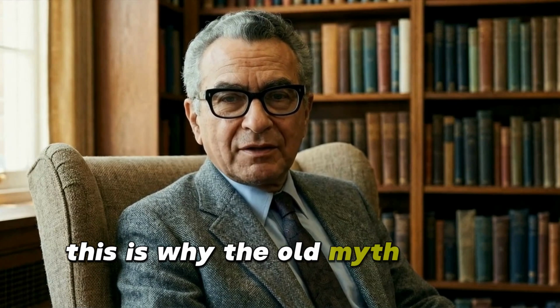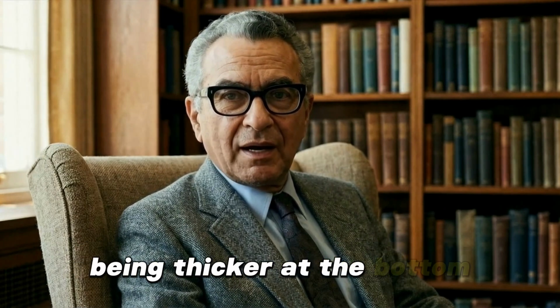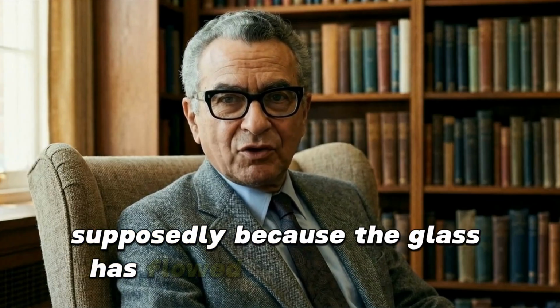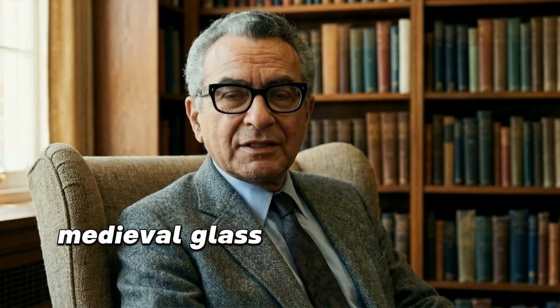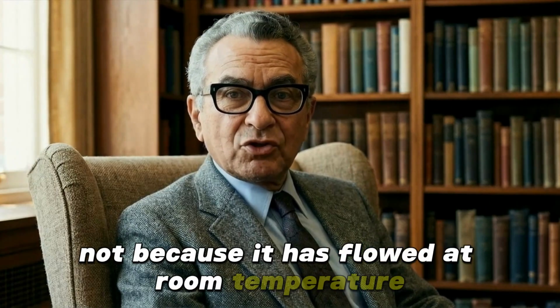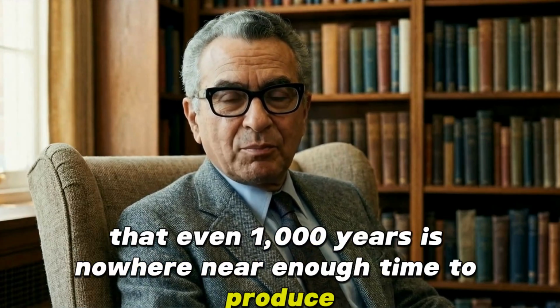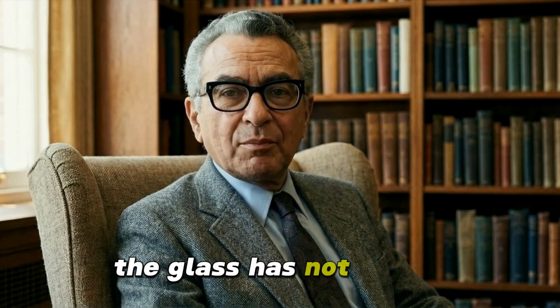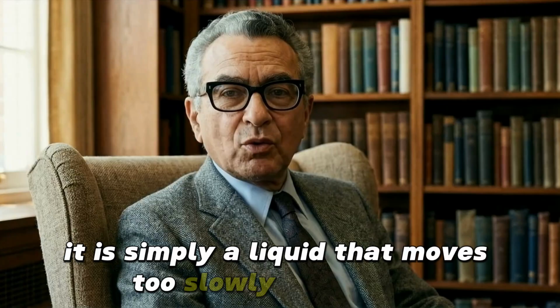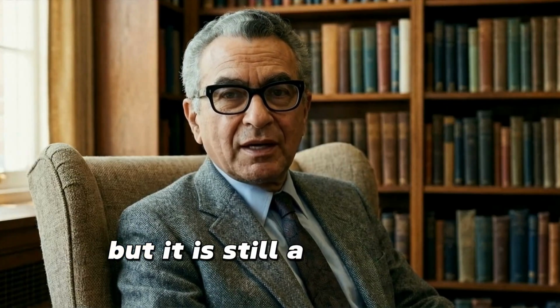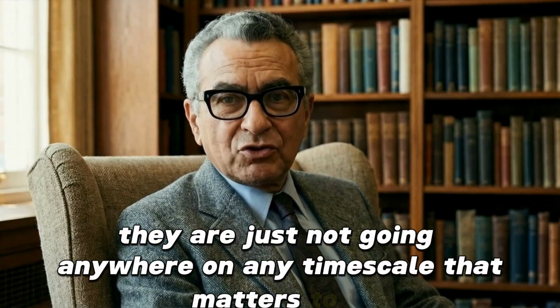This is why the old myth about ancient window glass being thicker at the bottom, supposedly because the glass has flowed downward over centuries, is almost certainly wrong. Medieval glass is thicker at the bottom because of how it was made, not because it has flowed. At room temperature, the viscosity of glass is so extreme that even 1,000 years is nowhere near enough time to produce measurable flow. The glass has not moved. It is simply a liquid that moves too slowly to observe. But it is still a liquid. The structure is still disordered. The molecules are still in a liquid arrangement. They are just not going anywhere on any time scale that matters to us.